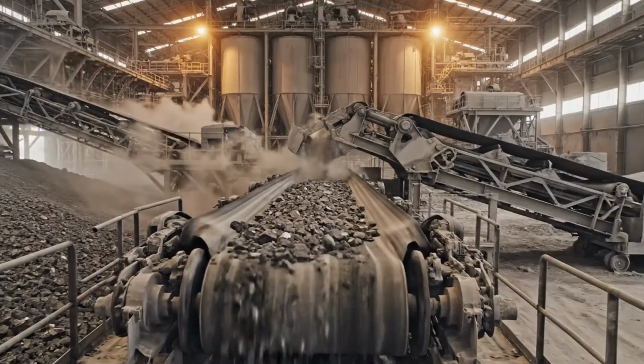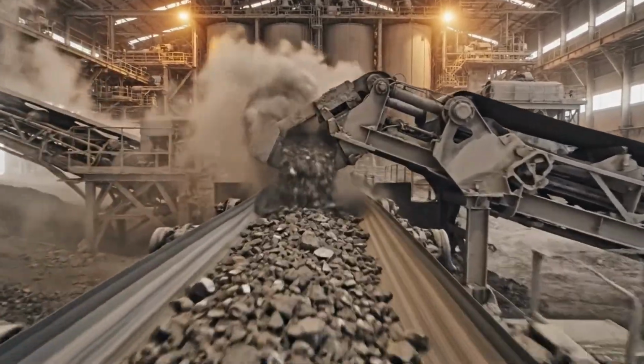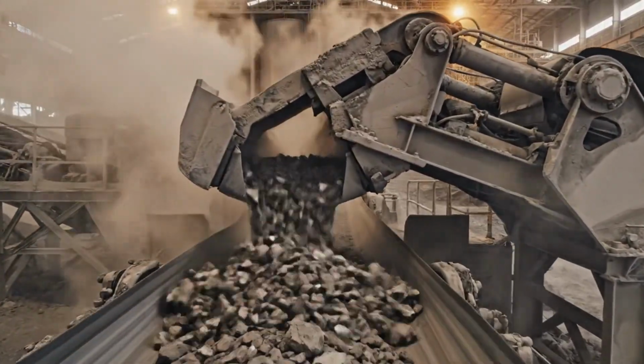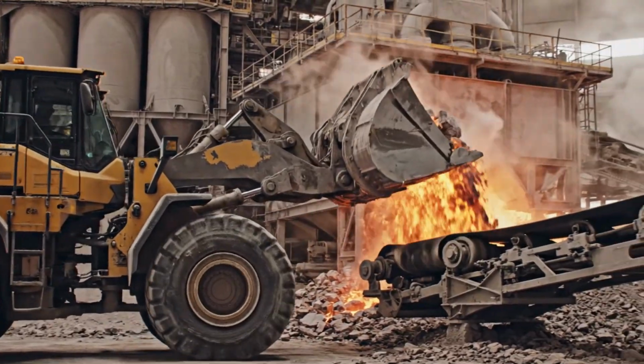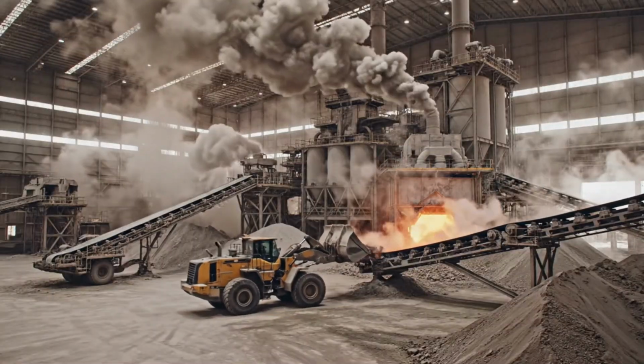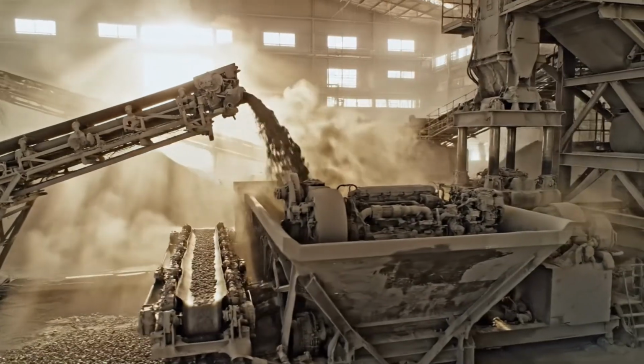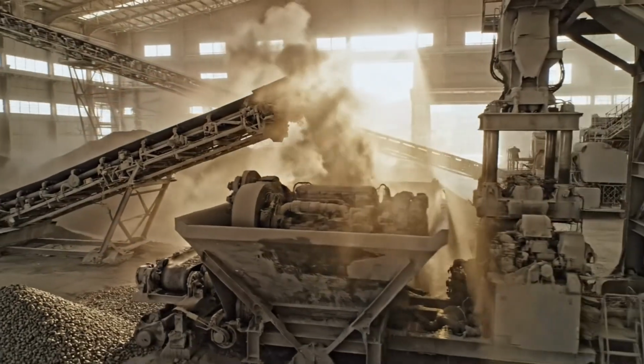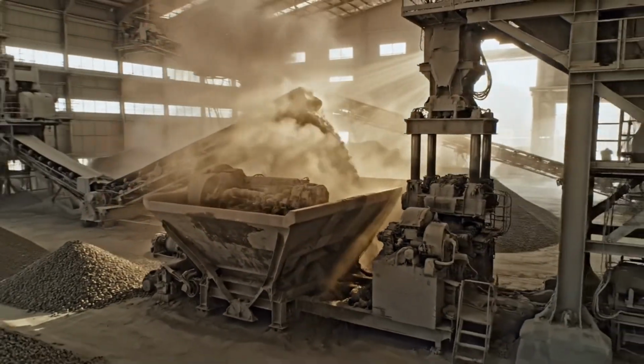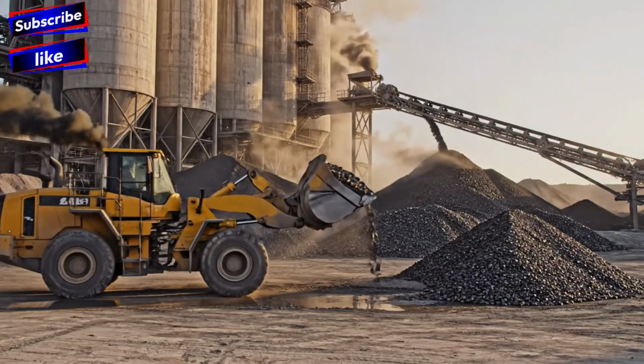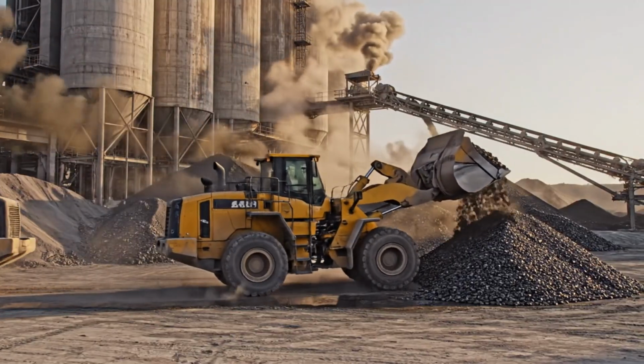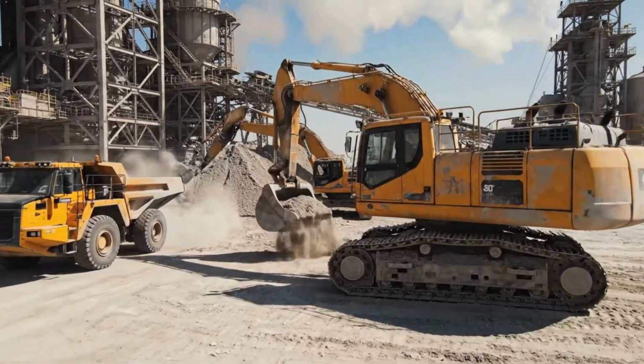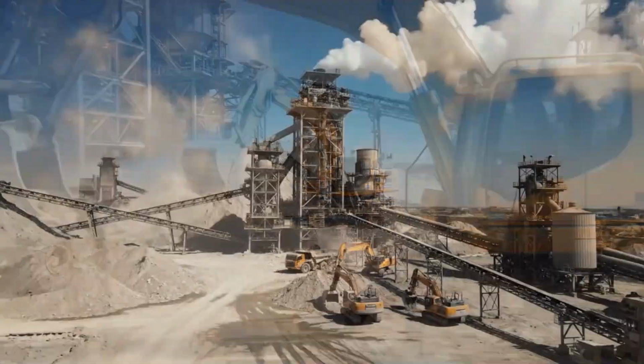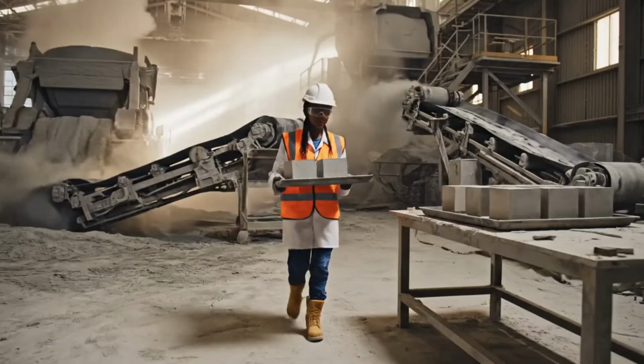At this point, the basic cement material has been formed, but it is not yet finished. Clinker is now mixed with a small amount of gypsum. This mixture is ground into a very fine powder inside cement mills. Gypsum controls the setting time of cement, making it usable in construction. The result of this grinding process is the cement powder we recognize.